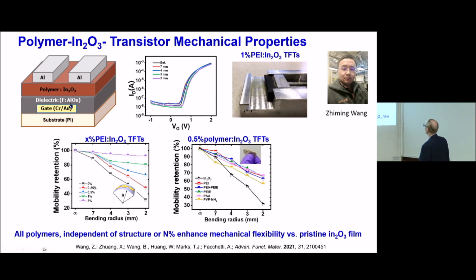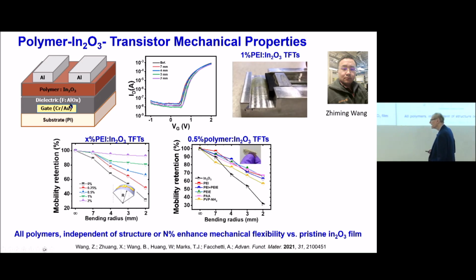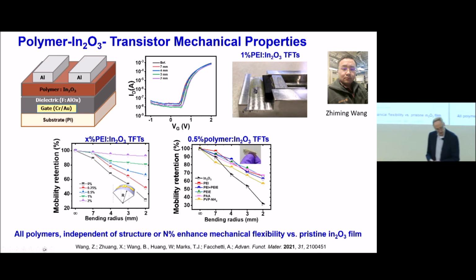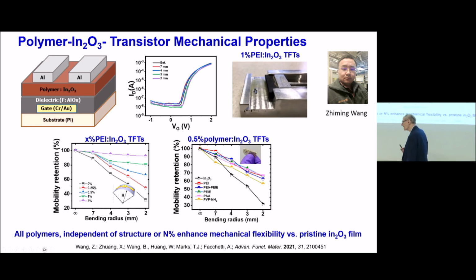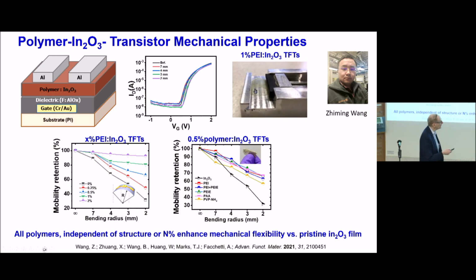So this is the work of Zhiming Wang, and what he was looking at, this is a machine he made to actually measure the mobility as we flex. So this is basically indium oxide with just a 1% PEI, and we've made the indium oxide, and it's on a flexible plastic substrate. And here you can see it can flex back and forth, and the pale yellow color is the PEI in the polymer matrix.